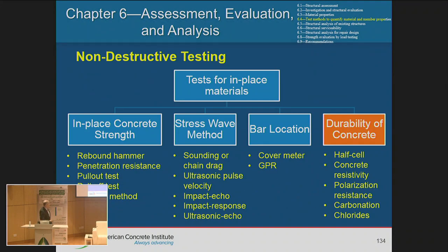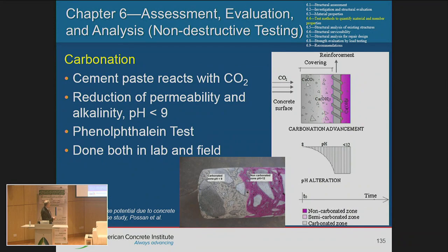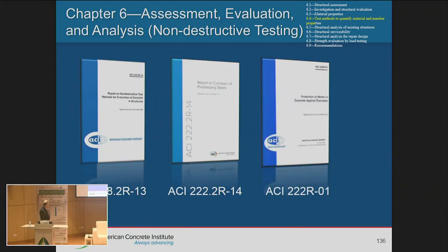Durability of concrete, we talked about the carbonation. Again, if you take a sample and apply the phenolphthalein test on the core, if it becomes colorless, that means there is carbonation, and you can determine how far the carbonation has penetrated into your concrete. But if it turns pink or reddish, that means you don't have carbonation in your concrete. Again, going back here, we have quite a bit of ACI documents that talk in much more depth about those tests, how to perform them, and the advantages and disadvantages of those tests.